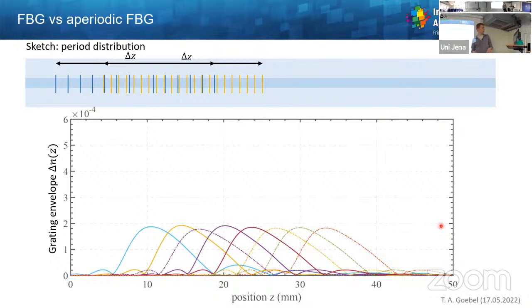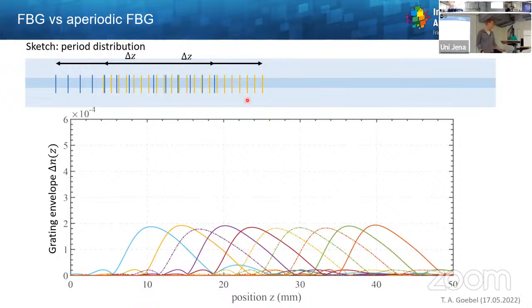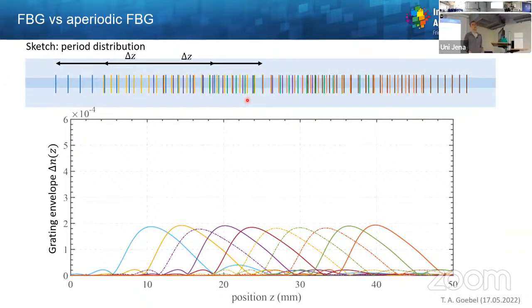And the more we stack these gratings together, what you can see on the top part is the period distribution. This is just a sketch, but if we add all these gratings together, this gets a very irregular pattern. And this is why we call this type of fiber Bragg grating an aperiodic fiber Bragg grating, because the period distribution is no longer periodic at all. It follows a somewhat random pattern, depending on the overlap of these different periods.